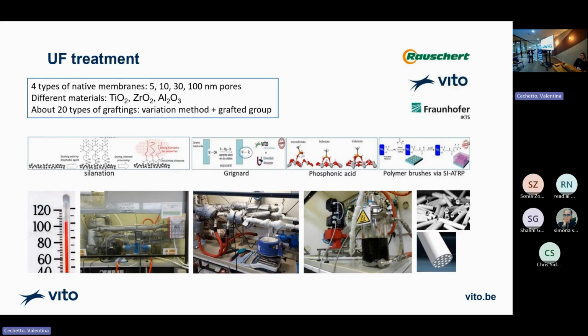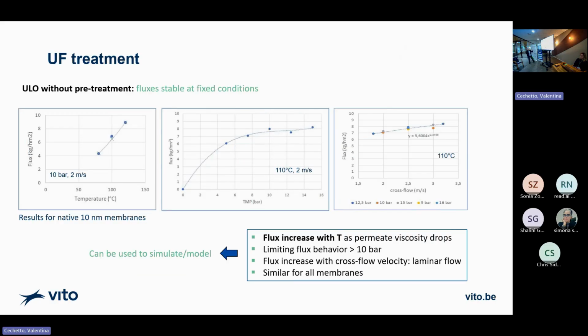Of course, we want to do this at high temperatures, so you see insulated systems there to be able to treat it. What we found, looking at the fluxes here, is that it is very dependent on the temperature. And the temperature is the main way to increase your flux. It's also very nice to see that it evolves nicely with the viscosity of your permeate, not of your feed. In this case, it's really very different, but it's the permeate which goes through the membrane, of course. We have limiting fluxes because of all these dirty impurities in there. Around 10 bar is a nice way to process. And we have also some influence of cross flow, following actually laminar flow behavior. So we have ways to simulate and to model this system.